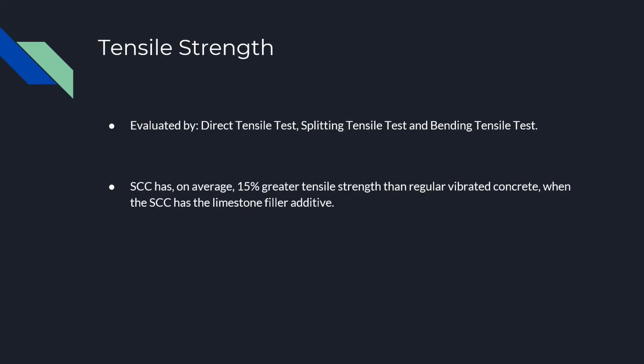In order to evaluate the tensile strength of SCC, three main and well-known methods of testing are used. All the experiments are conducted to measure and record the resistance of the SCC to breaking under tension. In a sample of test subjects, data obtained displayed that during the splitting tensile test, SCC that had the limestone filler had, on average, 15% greater tensile strength than regular vibrated concrete.